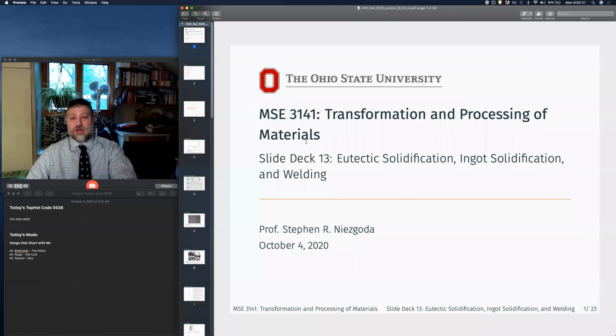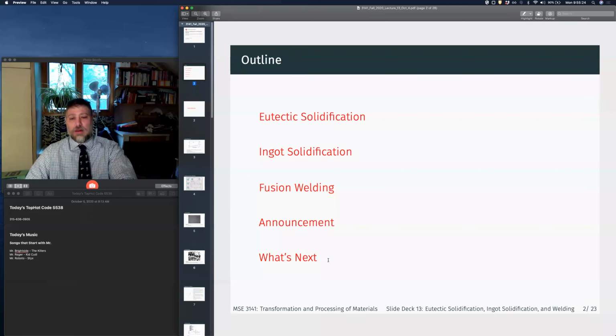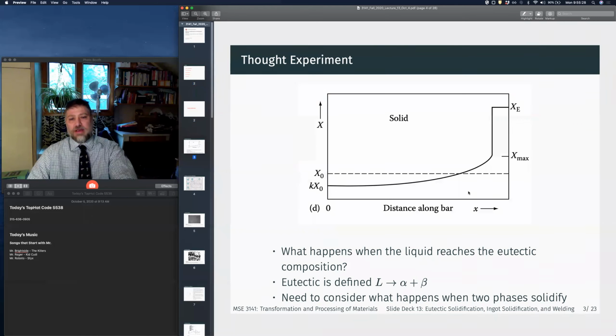Right? So that's sort of the topic, right? If we think about here, we have the composition profile that we get from our Scheil equation. And the question is, what happens when we reach this eutectic composition? Remember, the eutectic is defined as liquid freezes to both alpha and beta. Back here, we're freezing into the single phase alpha region. But when we're in this eutectic range, now we have a mixture of alpha and beta.